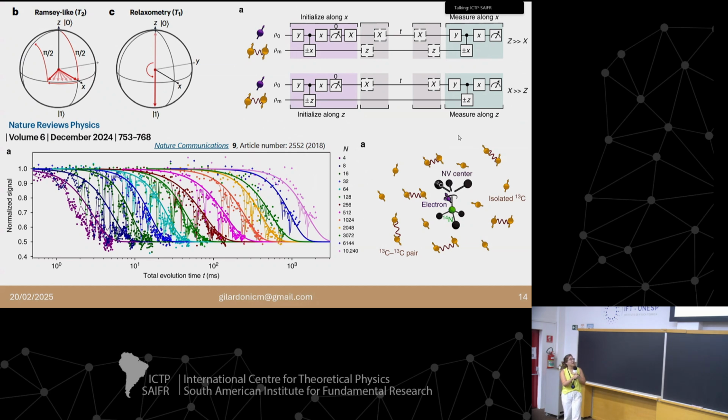But what you can see, and what would look like noise to any reasonable human being, they can actually map out into the interactions of the NV center with individual carbon-13 atoms in the lattice, right? So they can use a measurement like this and the behavior that they observe here to actually identify the individual positions of carbon-13 atoms in the lattice. And they do this, I think, in this work up to 27, but they've done that to 51 now. So they can identify individual interactions between the NV center and these carbon atoms. And from the magnitude of that interaction, they can map out the position.